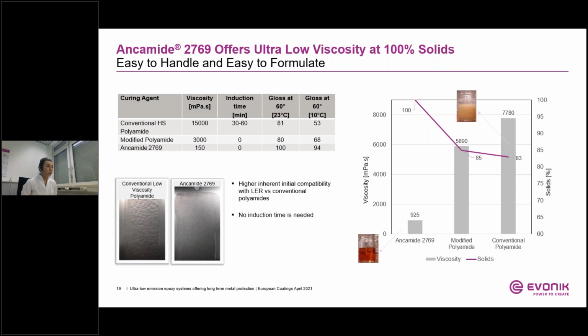As you can see, the viscosity of 2769 is 150 millipascal second, and it offers improved resin compatibility without the need of further modification, which is reflected here by the high gloss in cured coatings. Due to good compatibility of 2769 with liquid epoxy resin, no induction time is needed to achieve good surface appearance, and good surface wetting can be ensured. Even at lower temperature, tack-free, blush-free surfaces can be obtained.